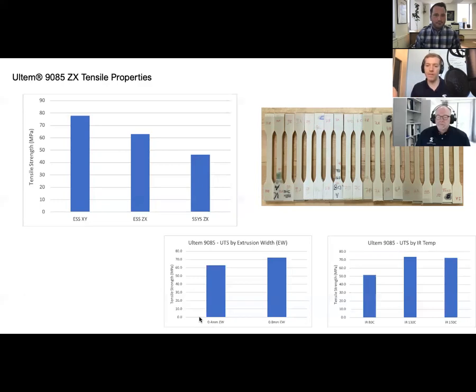We did a round robin study looking at things like nozzle size, speed, nozzle temperature, and the chamber IR settings that we applied. We also compared it to some plaques that we printed in the Z direction on a Stratasys platform, where a partner printed us some specimens. Up in the top left-hand corner, I have a comparison between XY properties. For all Ultem 9085 printed in the direction of the tensile strain, we were seeing about 78 megapascals for strength. So you get a little bit of an orientation effect there. In the Z direction, what was surprising to us is that we were seeing up to about 63 megapascals.